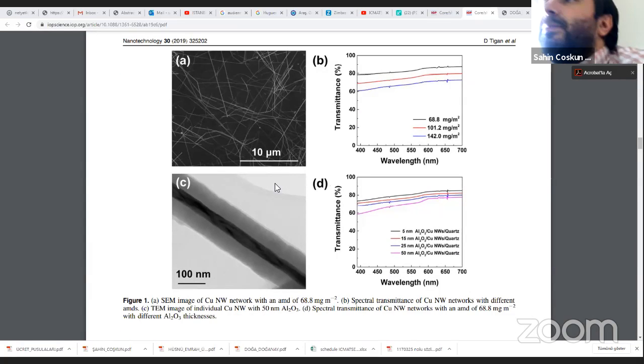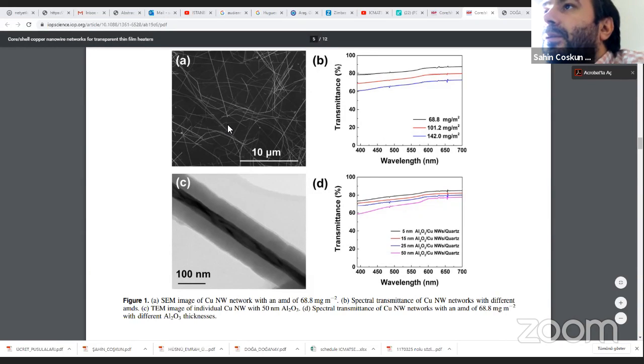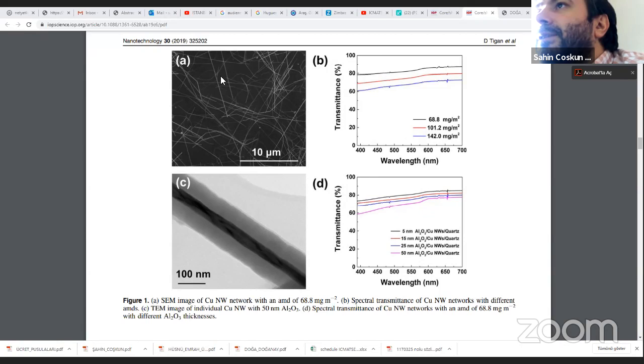Okay, so here is the point. These are copper nanowires. They can be coated on a surface as two-dimensional networks, but as you can see, they don't form a continuous film. In order to increase their stability, it's possible to coat very thin alumina films on those nanowires via atomic layer deposition. Here is the example. The core is the copper and the shell is alumina. And on those materials, alumina can be coated conformally. It's not like a continuous 2D structure, rather it can be considered as a 3D structure. Generally up to maybe 50 nanometers, they're not very crystalline. With some post-processing, it's possible to increase their crystallinity.